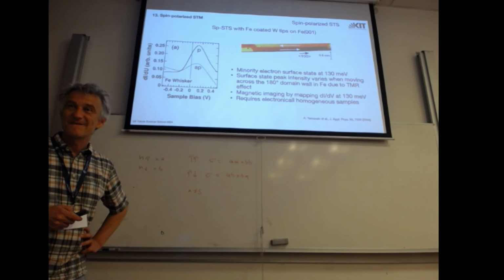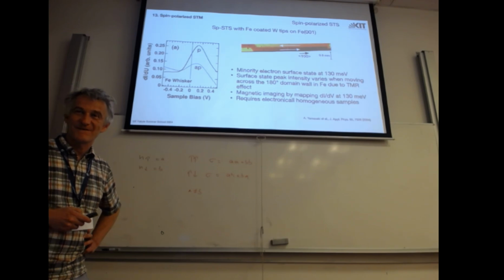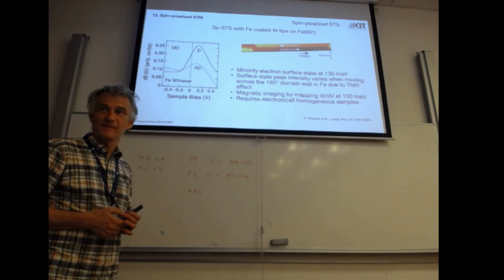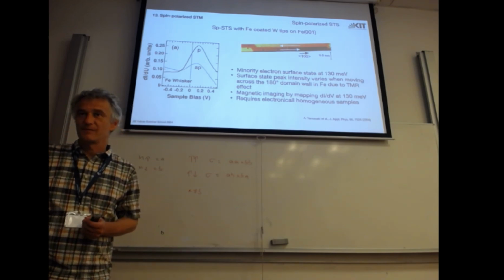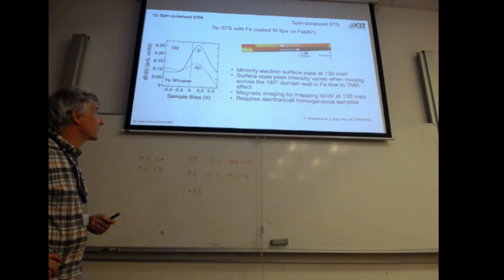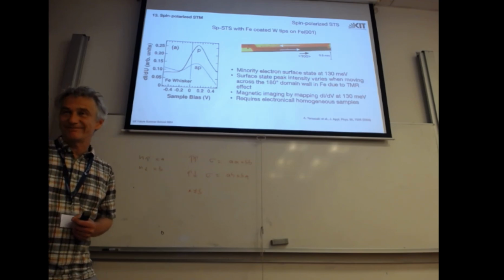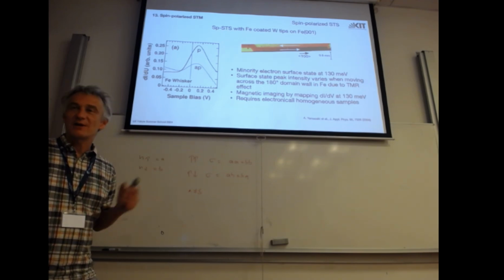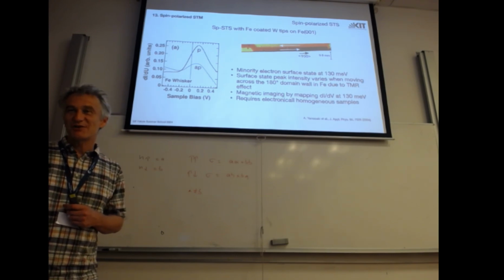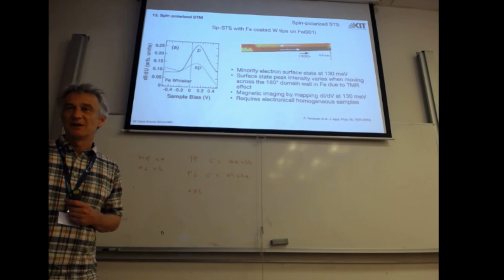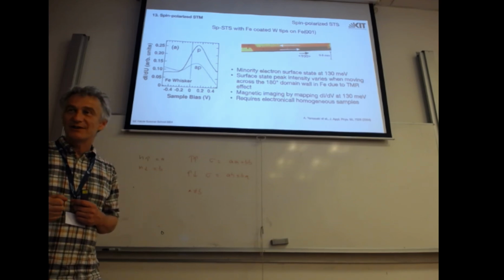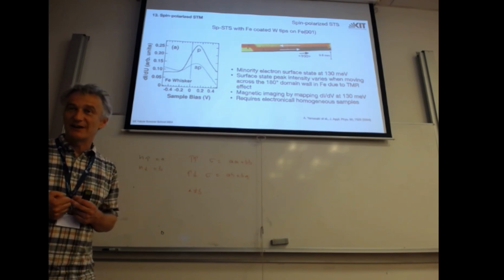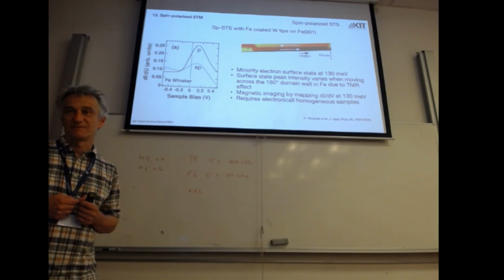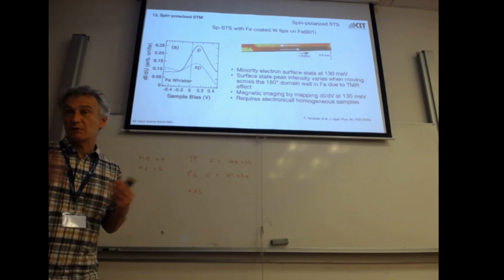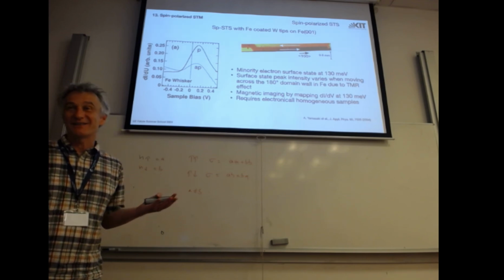I didn't exactly get this set up. So you take, let's say, a thin wire of iron. Our tip is actually a tungsten tip that we coat a little bit with iron. It's a normal tungsten tip, and then we deposit some iron atoms onto the tip, a film of, let's say, 5-6 monolayers, and this film is ferromagnetic and is at the end of the tip. You could also take a bulk ferromagnet, or for that matter, an anti-ferromagnet, which is also spin polarized.